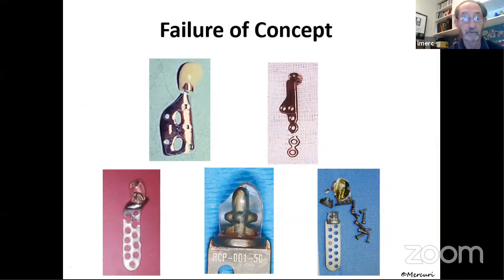Or other failures of concept, where we're talking about a very thin neck for a condyle, a very thin ramal component, and the use of polyethylene. This is not polyethylene. This is polymethyl methacrylate. Okay, this is denture material, clear denture material. And when this device was devised, the idea that the surgeon had who devised this was that the condylar component would wear down and remodel just like the normal temporomandibular joint does with bone, that you get a remodeling process. Well, that's not reasonable because what happens to all of these particles that get out into the periarticular tissue? And finally, this was a metal kind of device that only fractured. A bad idea to use metal against metal.